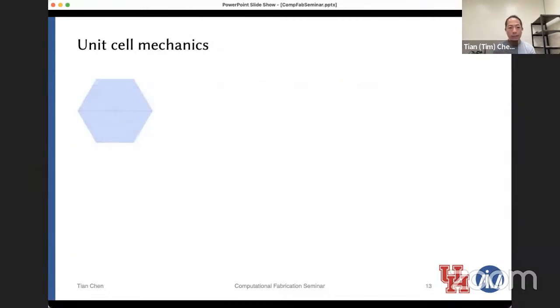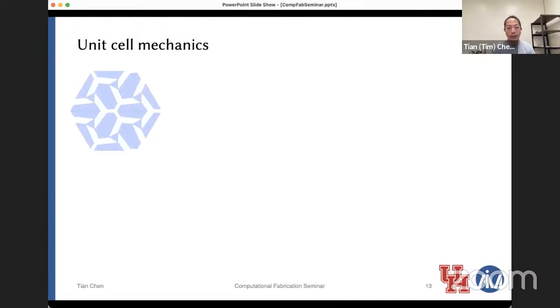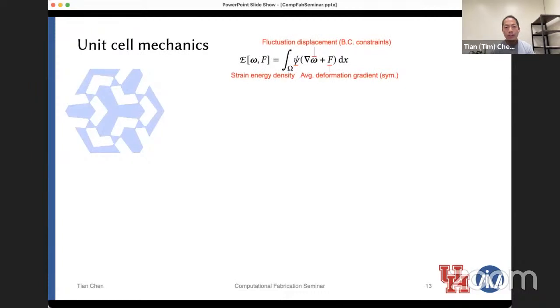So we turn to FEM and we notice that there's a quantifiable strain that happens at the middle of the expansion, which I denote here in red. These red regions are actually the stretch of the material. And this red region closes up once we fully expand the unit cell. It closes back down to a completely kinematically compatible state. So we built our own unit cell simulator that attempts to minimize the total energy of the system by applying an average deformation gradient.